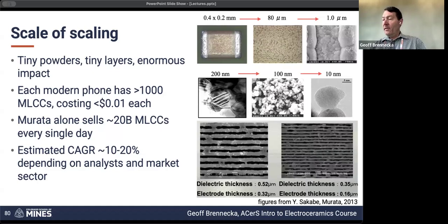So this top layer shows a packaged capacitor all the way down to the individual layer. This center row is showing just the example of the particles themselves. So in a sintered capacitor, this example shows grains on the order of 200 nanometers. And now as the industry has progressed, they're operating with particles and powders on the order of 10 nanometers. So just continuing to shrink and shrink and shrink.